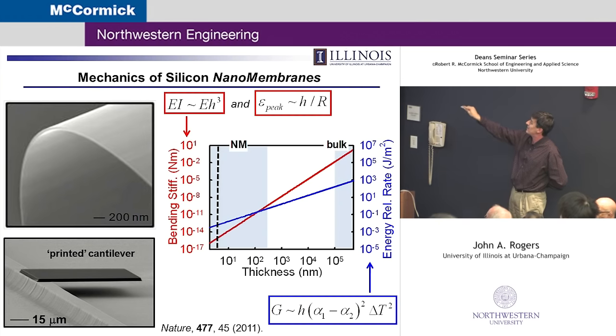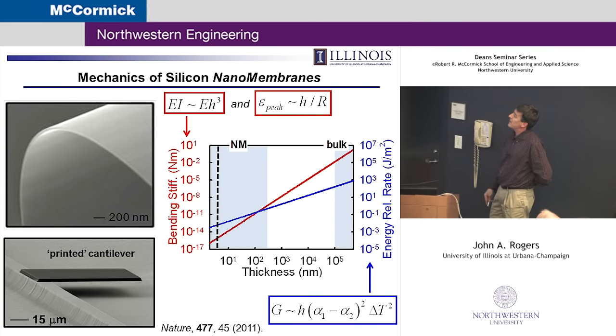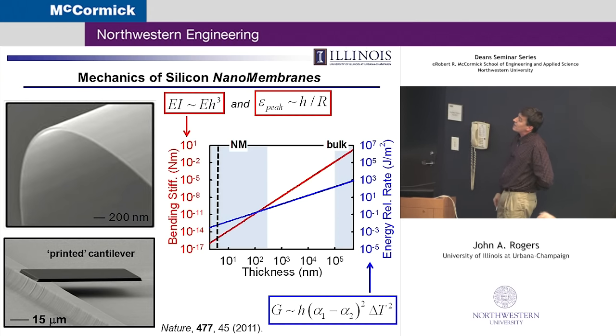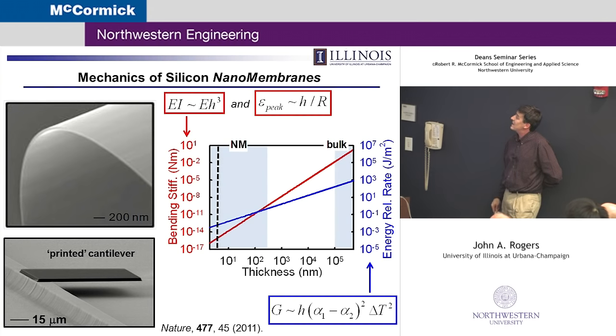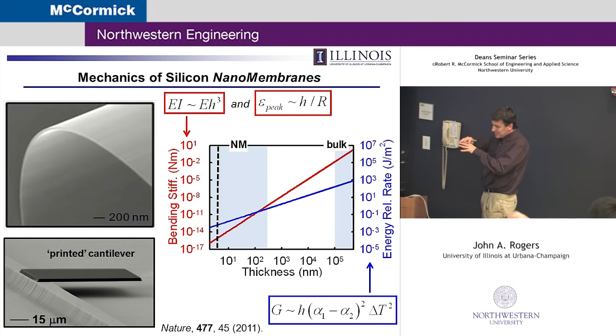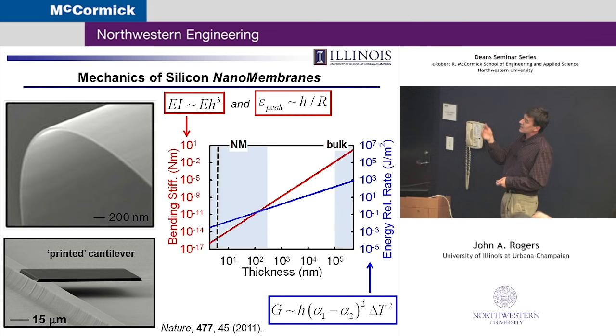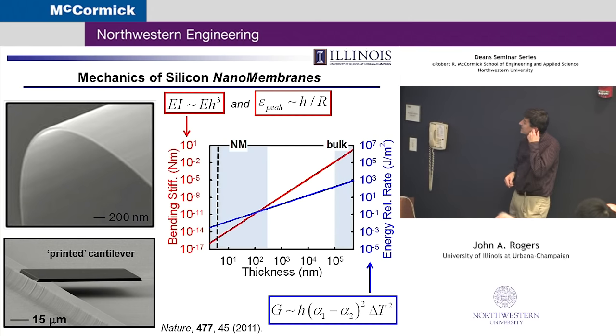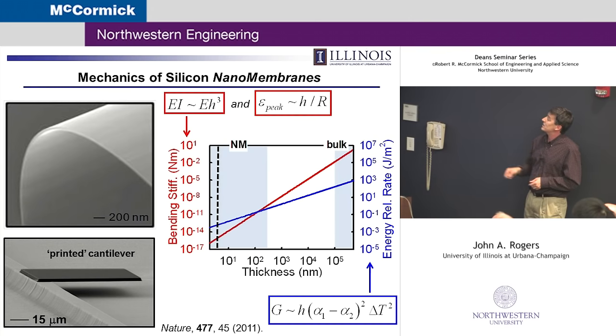But whenever you change something by 15 orders of magnitude, that really has a qualitative effect on the way that you think about that material. So it goes from being a rigid plate of glass to a floppy noodle. And you can kind of see that here. Very, very flexible, very low bending stiffness in that sense. The other consequence of scaling thickness down is that for a given bend radius, R, the peak strain associated with bending is going down linearly with thickness. So it's not only floppy, but it becomes very bendable as you drive the thickness down. So those are two good aspects, appealing aspects of making silicon very, very thin.